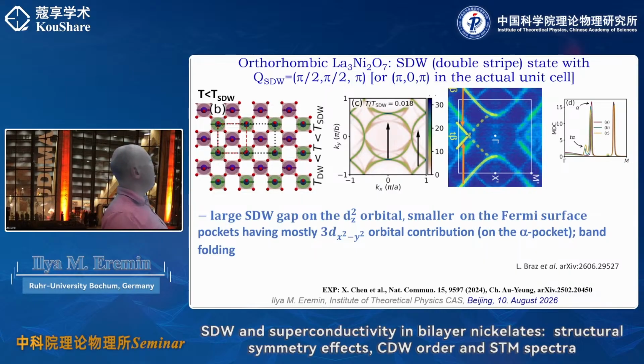And this you very nicely see if you now plot the MDC along the gamma-M direction, for example. You clearly see, and this is the reduced temperatures, that the lower the temperature is, the more spectral weight is taken from the true band to the folded band. So our interpretation is that what they claim to be a pure spin density wave gap is actually a result of the folding of the Fermi surfaces.